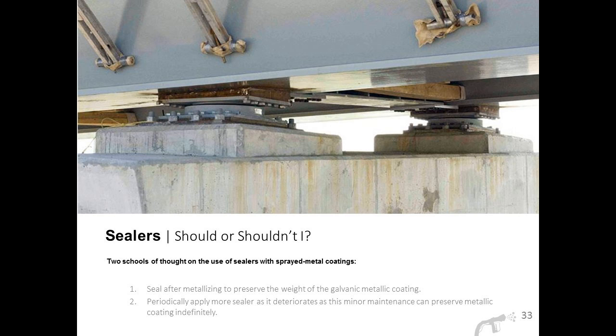And finally, as we talk about materials, the question of sealers comes up quite a bit. Basically, a sealer is a non-viscous liquid that's applied to the metallized surface to reduce the permeability of the coating and preserve the weight of the galvanic metallic coating. So if you're going to use a sealer, it's important to use one of sufficiently low viscosity to get in and fill any of the permeable little spots in the metallized coating.